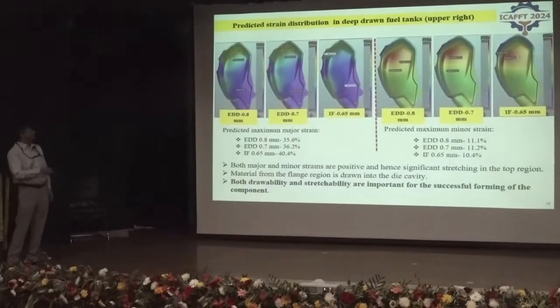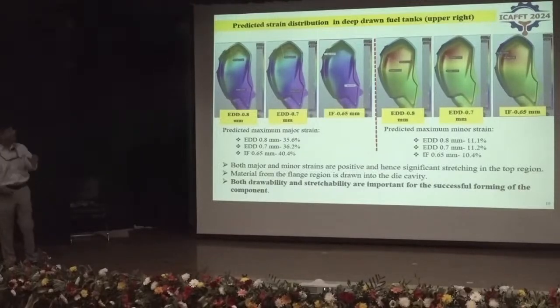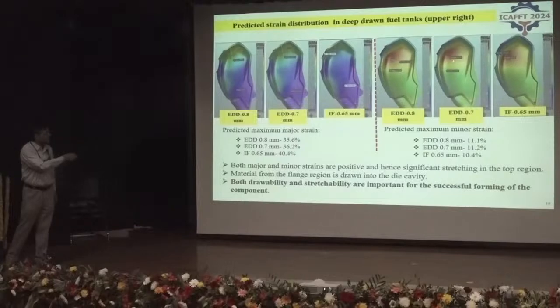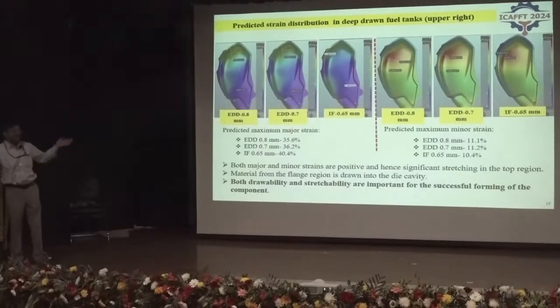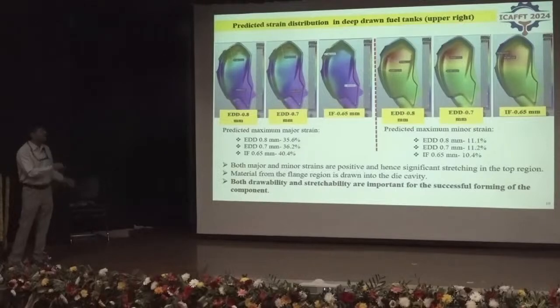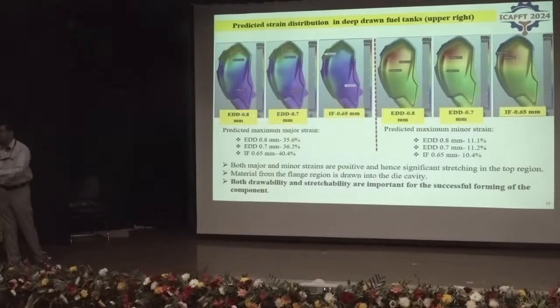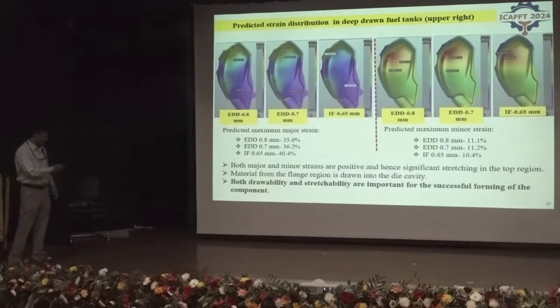And this shows the major strain and minor strain distributions in the simulated parts, and we can see that IF steel can take a larger amount of strain. In this portion we have seen both the strains are highly positive, indicating that there is a large amount of biaxial stretching in this portion where the depth is maximum. But in the other regions, the material is drawn from the flange into the wall region. So to resist thinning in the wall, drawability is also extremely important. Therefore both stretchability and drawability are very important to manufacture this part, even though we generally say fuel tank is made by deep drawing. But stretchability is also extremely important.